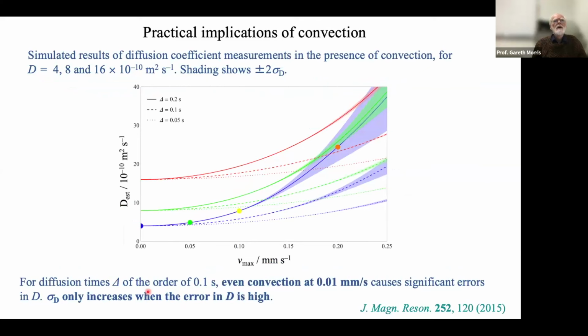What's the effect? Unfortunately, the effect is that even slow convection gives us a measurable shift in diffusion coefficient. But unfortunately, we don't actually see the uncertainty increasing until we've got really severe convection. So we should always be skeptical about our measured values of D if we haven't taken precautions to either cancel or minimize the effects of convection.